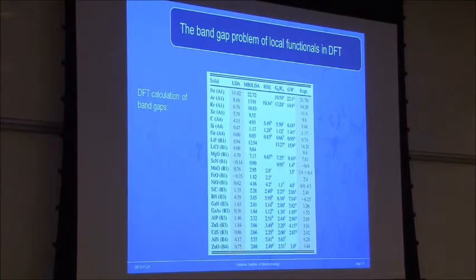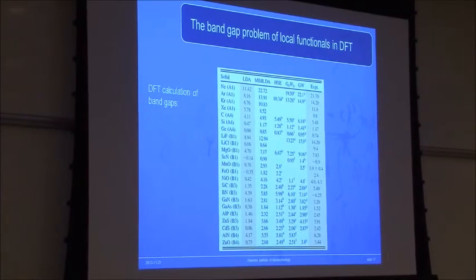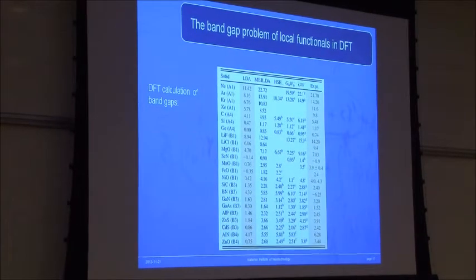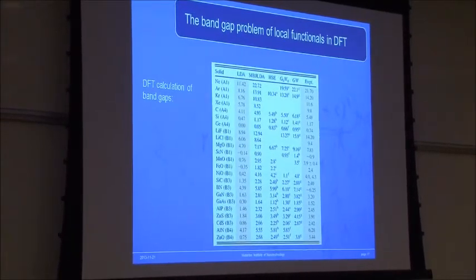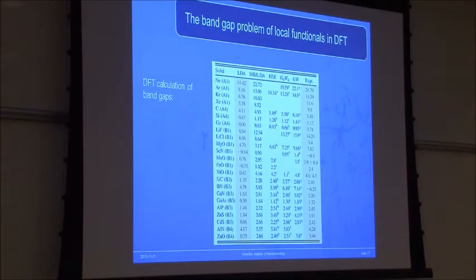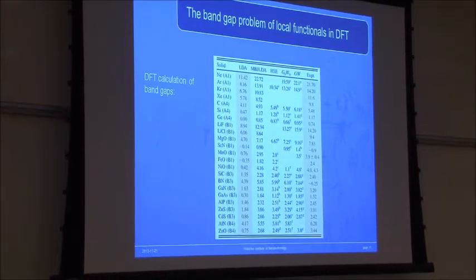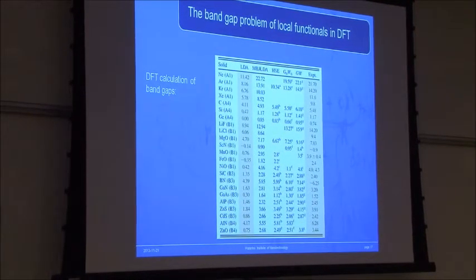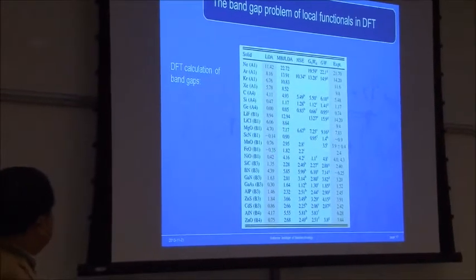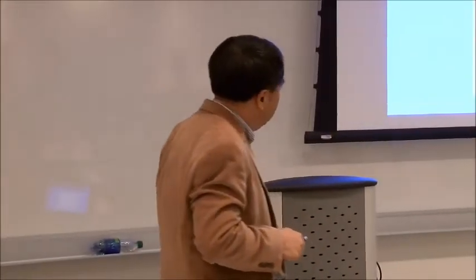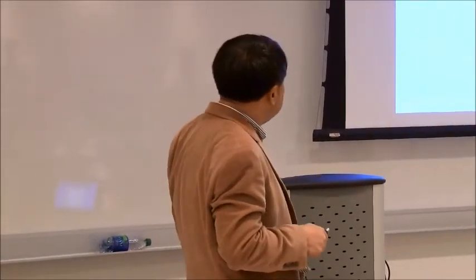Again, solid state physics people make progress in this. We have density functional theory, and density functional theory is an approximate theory, so not everything is right. One of the things which is completely wrong is the band gaps. If you use some functional called local density approximation, which is part of the approximation used for density functional theory, you will get a band gap which is half of the experimental band gap, so to speak. This is a well-known problem. If you do very high-level theory, like exact exchange and so on, you get reasonable results, but these are very big calculations and you can only do 50 atoms.